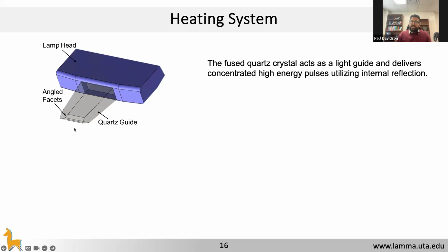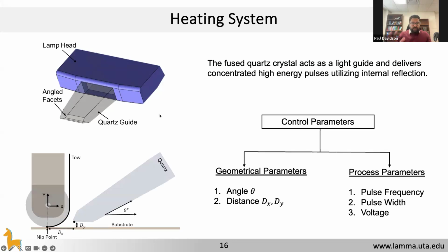So if one were to think about what are the parameters that can go into the processing of it, it depends on the location of the quartz with respect to the tows and the substrate. So that means there is a geometrical parameter, and of course, what the power of the lamp is. And the power of the lamp is controlled by the pulse frequency, pulse width, and the voltage. So essentially, there are two process control parameters for our system. So our question was, how can we use these control parameters to get the temperature we need at the nip point? That temperature is the temperature of the tow as well as the temperature at the substrate.